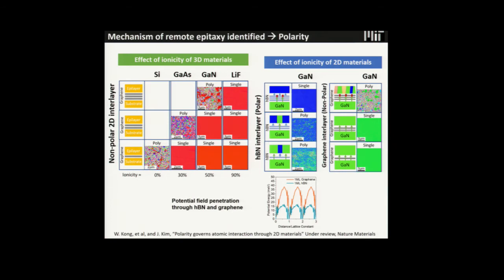Okay, what's the difference between this guy and that guy? Gallium arsenide has ionicity in its bonding, 30%. Okay, but then we can try more. Because gallium nitride has a 50% ionicity, you can grow single crystalline gallium nitride through bilayer graphene too.